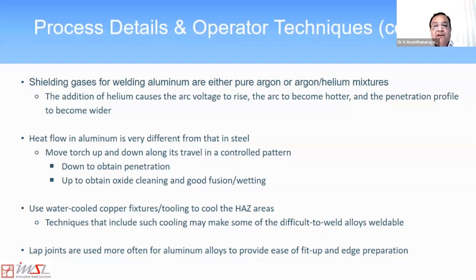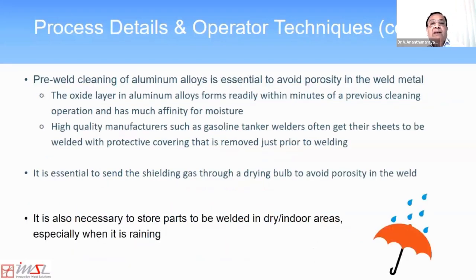And lap joints are more often used with welding aluminum alloys to provide ease of fit up and edge preparation. And pre-weld cleaning of aluminum alloys is essential to avoid porosity in the weld. As I mentioned, it's not a good idea to store aluminum alloy parts to be welded in open atmosphere close to a rainy area, for instance. And the oxide layer, as I mentioned, has much affinity for moisture. And the gasoline tanker welders in Tennessee that I mentioned always get their sheets to be welded with protective covering, somewhat sticky covering that doesn't leave any residue on the metal when they are removed. And they are removed just prior to welding, and then they weld it, and then they remove another covering about a couple of feet from the weld, so the covering doesn't get hot.